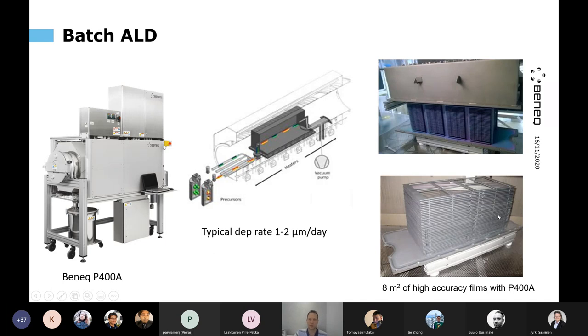Once after loading the substrates in the chamber, we close the reaction chamber, put it inside the ALD system, pump down to the vacuum pressure that we use and heat it up to process temperature. And then we start introducing these precursors one by one. So first precursor coming in, covering all the surfaces, any excess material going out. And then after that, second precursor coming in again, covering all the surfaces. And this way we continue as long as we need to get the film thickness that we are looking for.